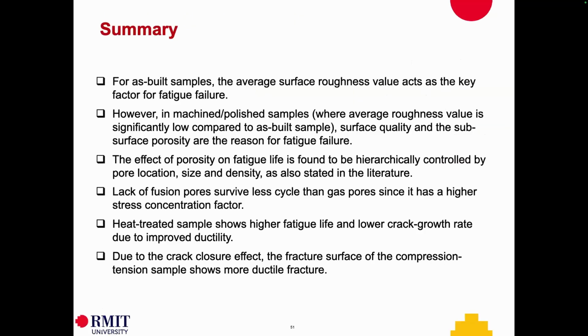So that's the summary. What we found in our work, particularly for the aluminum alloy as-built samples, the average surface roughness value acts as the key factor. If we use machine polished surface quality, subsurface porosity would be the reason, and that we should pay attention to. The effect of porosity is controlled by location, size, and density, in this order. So the pore locations are critical, and we need to remove pores on the surface. That will significantly degrade the fatigue life.